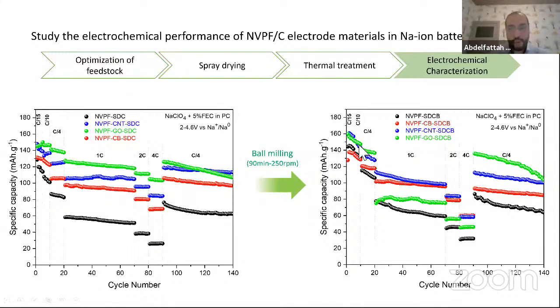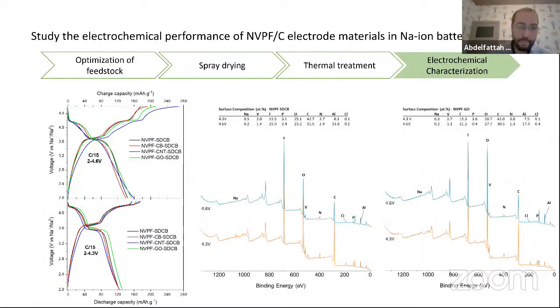But the one that is showing the best electrochemical performance after grinding is the one with carbon nanotubes, thanks to the positive effect of these carbon sources. Here also we were interested to optimize the voltage of cycling, the voltage window. This is where we make some XPS measurements to see why we have this extra capacity and how we can optimize the electrochemical performances. This is why we make some XPS measurements at different voltages.